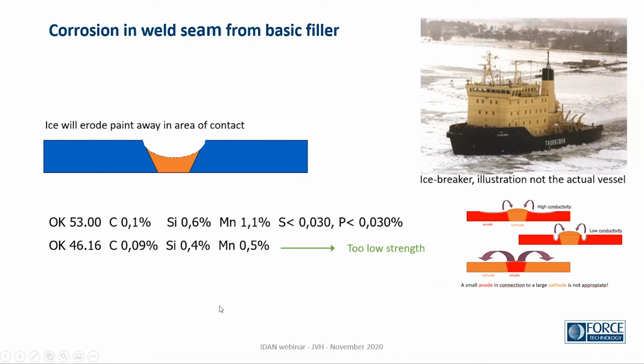A bit of an old example, perhaps, of selective corrosion in a weld metal was an icebreaker which was sailing in the north part of the Baltic Sea, and shortly after being taken into service, it was found that the welds were disappearing by corrosion, illustrated by this sketch here. And it's not this one, but I don't actually have a photo of the actual icebreaker.